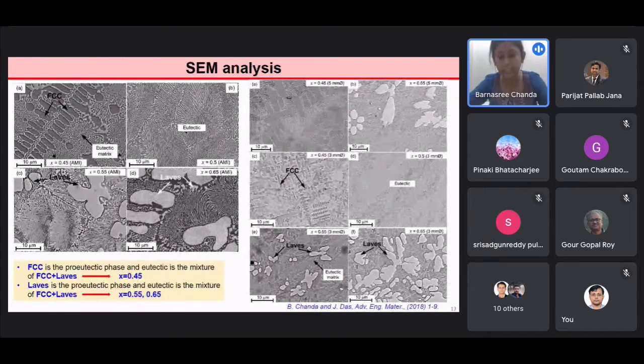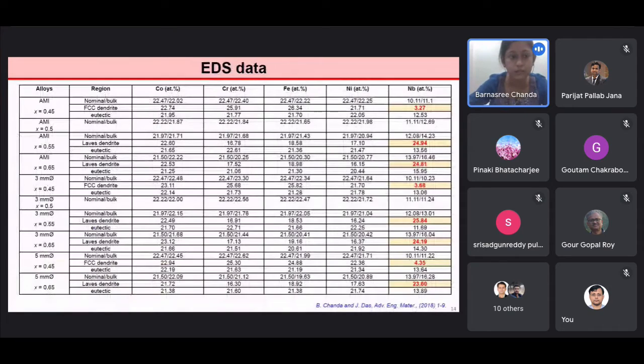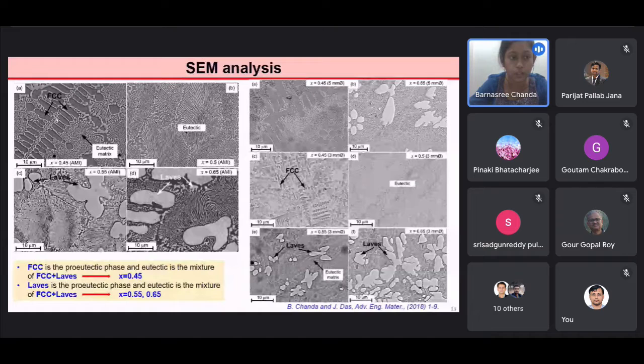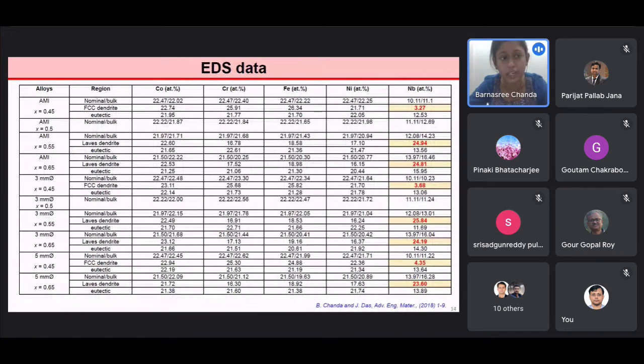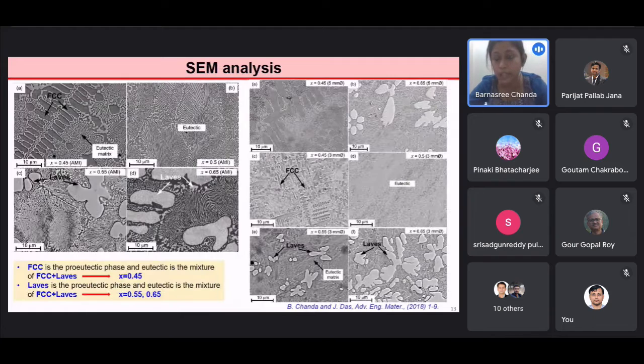Therefore, we move further to scanning electron microscopy analysis, and along with EDS data, we see that the pro-eutectic phases at 0.45 are of FCC type in a eutectic matrix, which is alternate lamellae of the FCC and Laves phase. And at 0.5, alternate lamellae of Laves and FCC phase can be seen. At 0.55 and 0.65, the dendrites are of Laves type. And the niobium concentration in the FCC phase is very negligible as compared to the Laves phase, where a higher concentration of niobium is present, which also supports the pseudo-binary phase diagram. Similar results can be seen in the suction casted rod. From this, we can conclude that with the addition of niobium, the microstructure varies from hypoeutectic to fully eutectic and then hypereutectic.